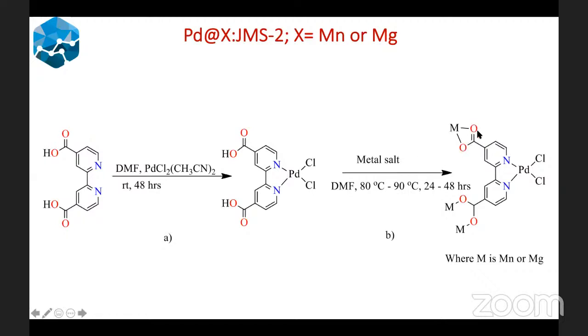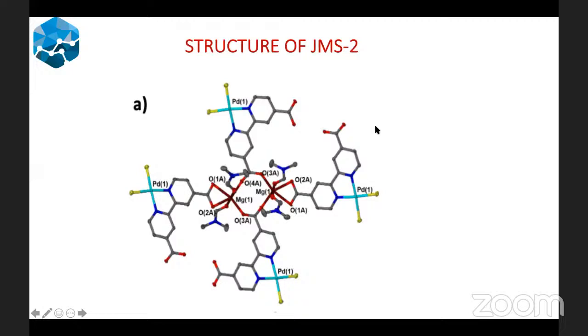We're able to isolate a metal organic framework in which your carboxylate moiety has 2 binding modes as illustrated in this scheme. So this is the structure of the MOF that we isolated. And as you can see, the metal center here, we used magnesium and manganese, so this could be magnesium or manganese. And you can see your palladium, which is coordinated to your chloride. And of course, at this metal center, you can clearly see that there is coordinated DMF, which is very important because it can be removed during activation to provide open metal sites, which enhance catalysis as well as adsorption of carbon dioxide.